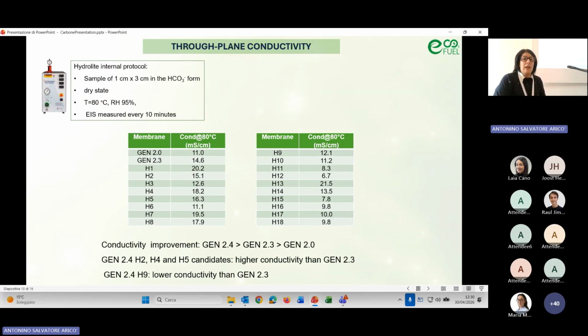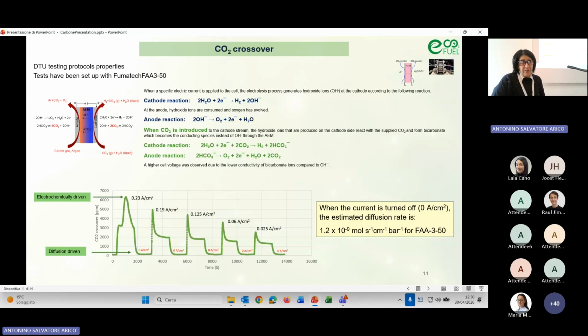Then at Hydrolite, the anion conductivity was measured in the through-plane section, with the Scribner test station. This test was carried out at 80 degrees and 95% relative humidity by impedance spectroscopy. In the table is reported also the comparison of the previous generation and the 18 membranes, and it's clear that the Gen 2.4 has higher conductivity than previous generation 2.3 and 2.0, and H9 also in this case shows a lower conductivity. So this is very, very important.